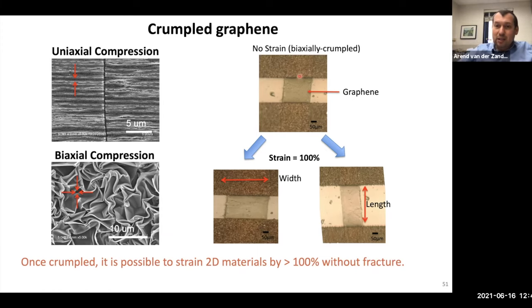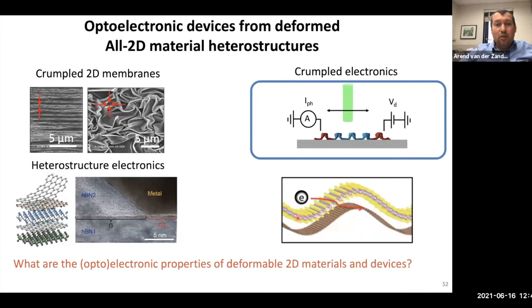You can actually see this on the right. So here we have crumpled graphene, and then we can now stretch it along one direction or the other, and you can see that it's getting longer, wider, or narrower. It's just the middle region, but it's not cracking. And so now we're going to take this idea that we can make heterostructure electronic devices by layering materials on top of each other and combine it with this idea of crumpling. Can we make a device where it can crumple and yet still work?